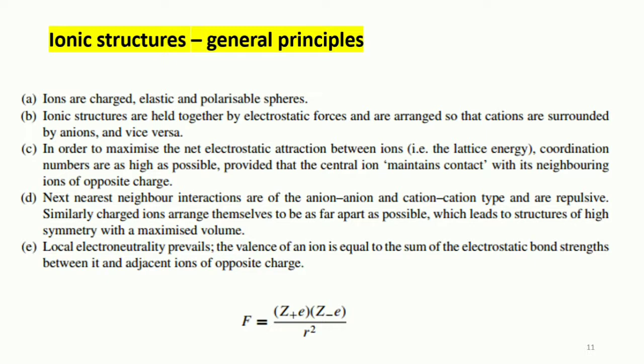the second of a set of rules formulated by Pauling for ionic crystals. Basically, the rule means that the charge on a particular ion, for example, an anion, must be balanced by an equal and oppositely charged ions. However, since these cations are also shared with their other anions, it is necessary to estimate the amount of positive charge that is effectively associated with each cation anion bond.